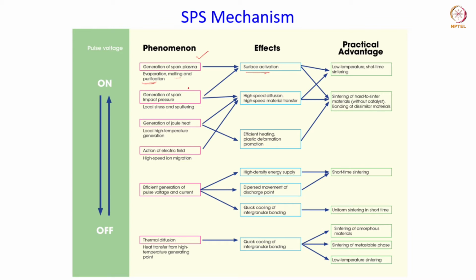Okay, then once the spark is generated, it will also exert some impact pressure on the particles, right? Because it is sparking. So you might have seen how sparking comes out with a force, right? So due to that, some kind of impact pressure will be provided when the spark is generated between the particles, and this basically leads to local stress and sputtering, and the effect of that is high speed diffusion and high speed material transfer for the neck growth that leads to densification.